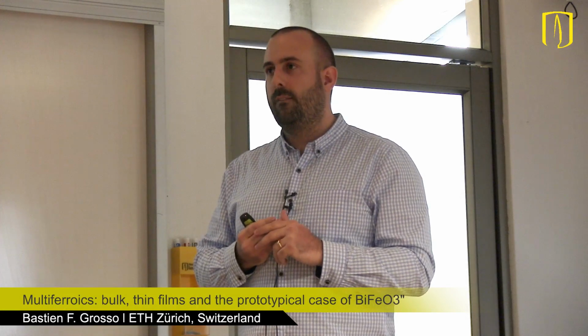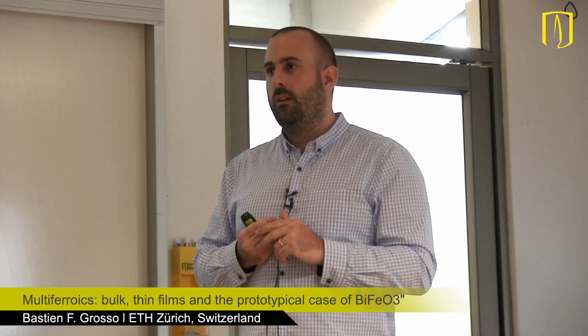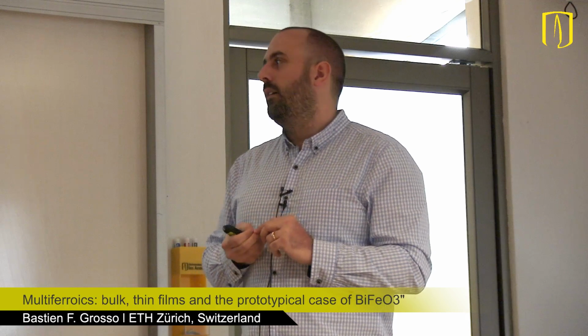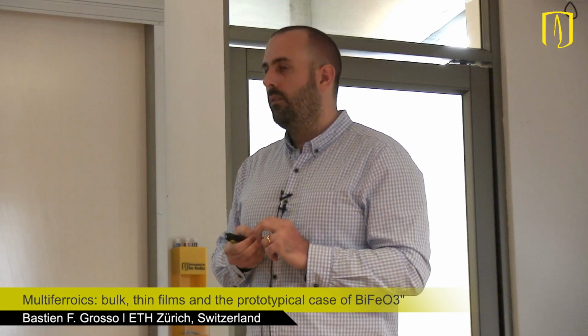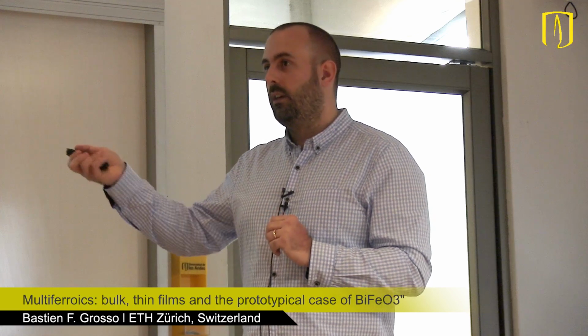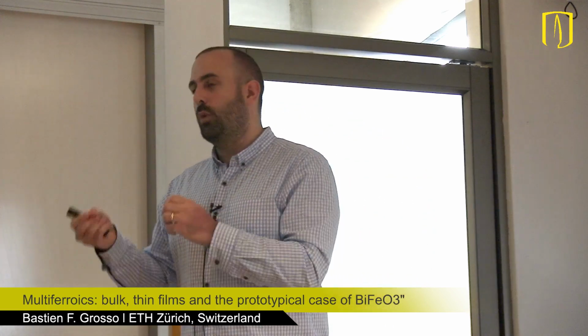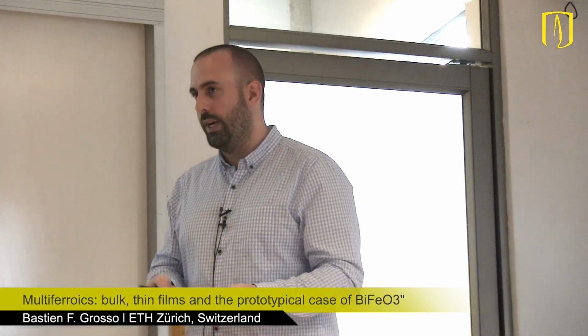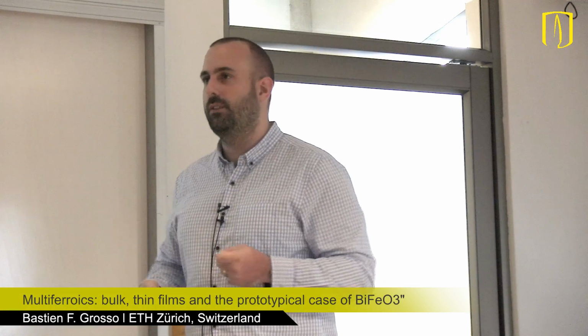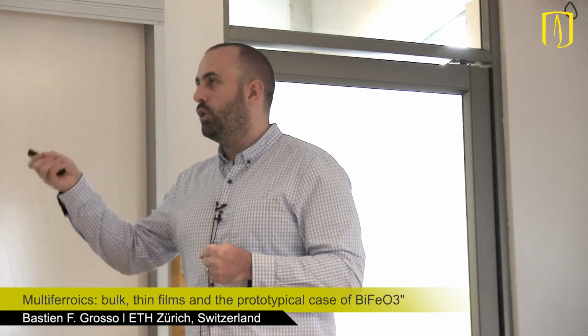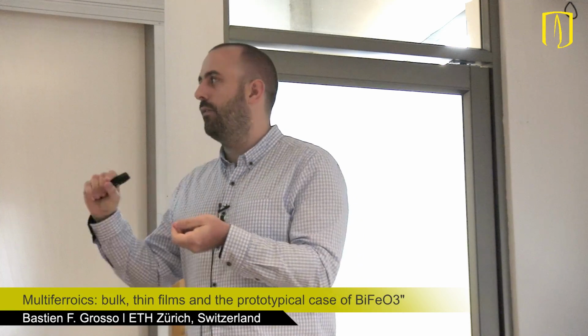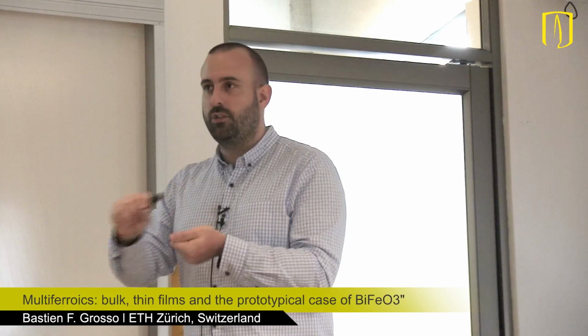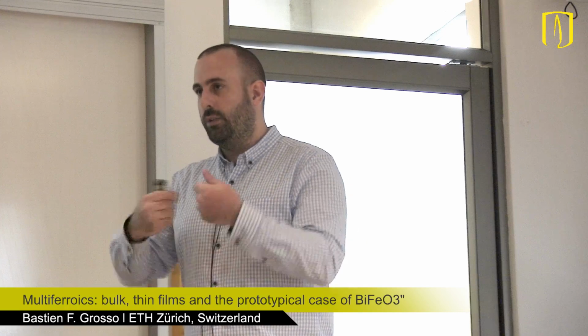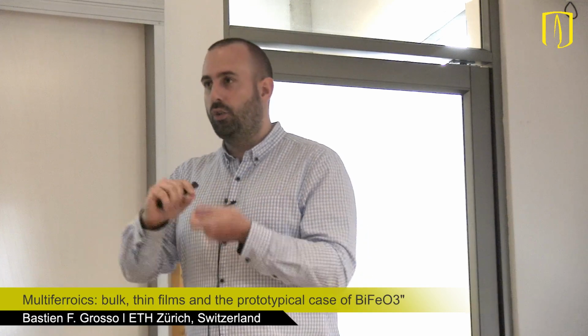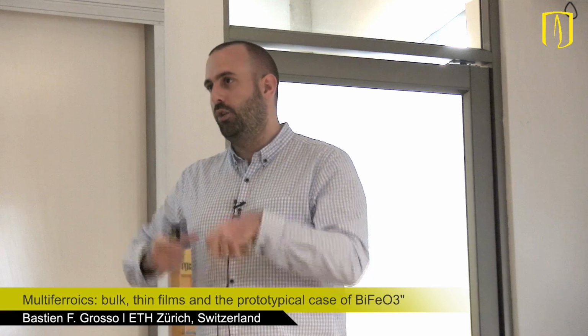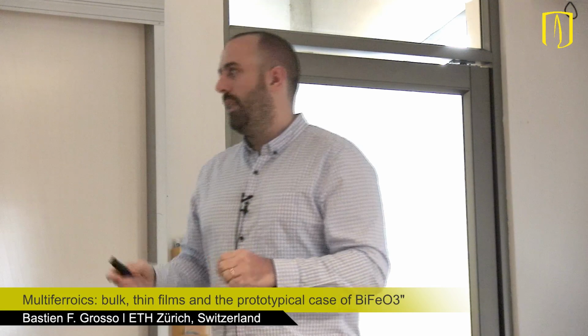Has this been synthesized in some single crystal form, or this is just a strain effect, like having this new phase? Yeah. This is just a matter of the strain effect between substrate and... So you mean that case here? Yes. So it has been tried, different heterostructures on the same strain, which I don't show here, but I'll talk about it tomorrow. So what they tried is to change, instead of the lanthanum bismuth ferrite, first you can change the concentration of lanthanum. When you increase the lanthanum, you go to more non-polar, or you change the dielectric constant of your material. So you change the screening, still on the same substrate.